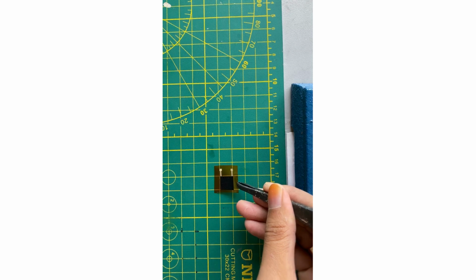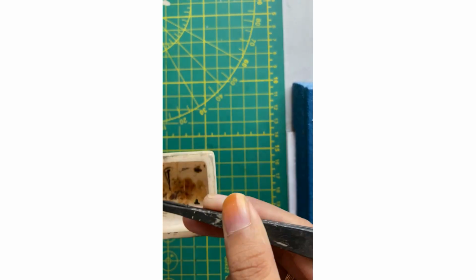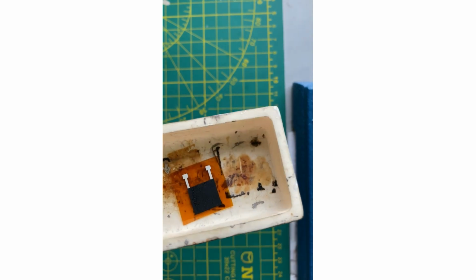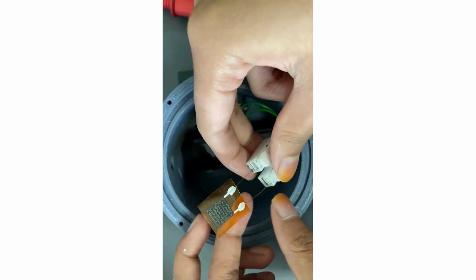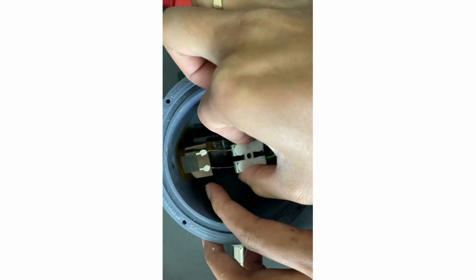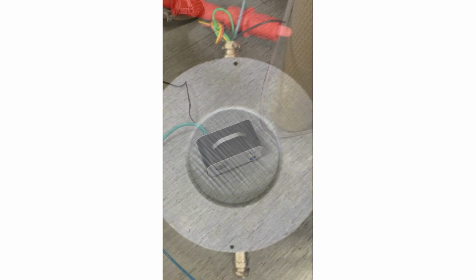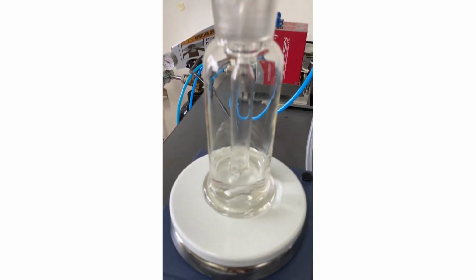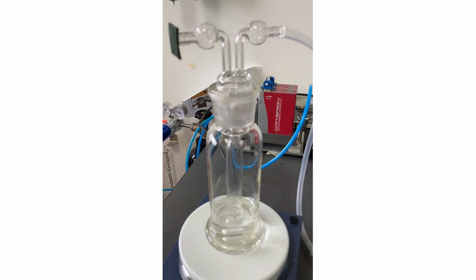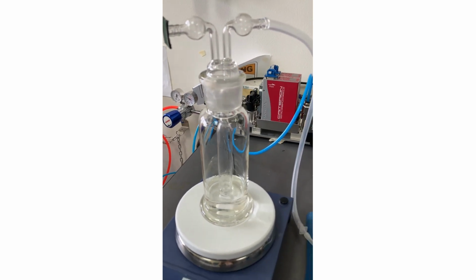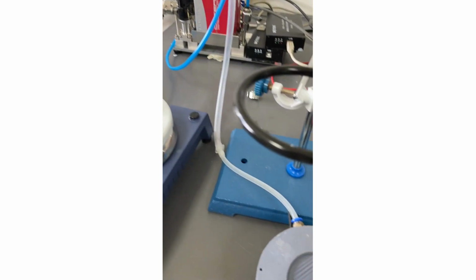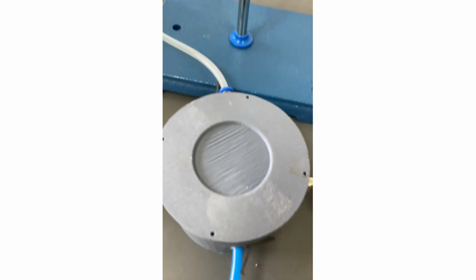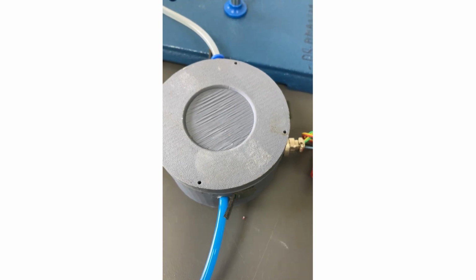This procedure was applied with two variables, one coated by one layer of sensing material and another by two layers of sensing material to cover the entire sensing area. This video depicts the process for measuring gas sensor response to acetone and ethanol. The acetone solution was filled in glassware and the vapor flowed inside the gas chamber via silicone hose. The solution was made by mixing 25 ml of acetone or ethanol with 25 ml of distilled water with a magnetic stirrer at 100 rpm for 5 minutes.